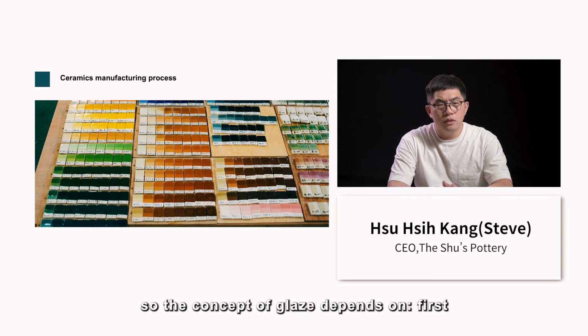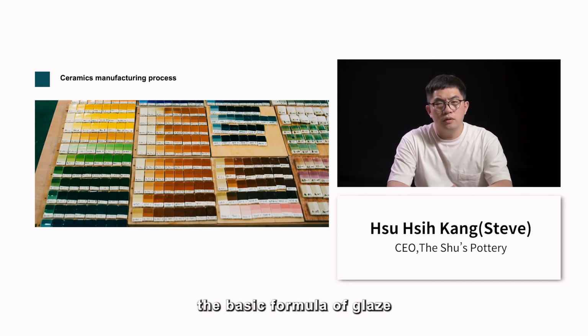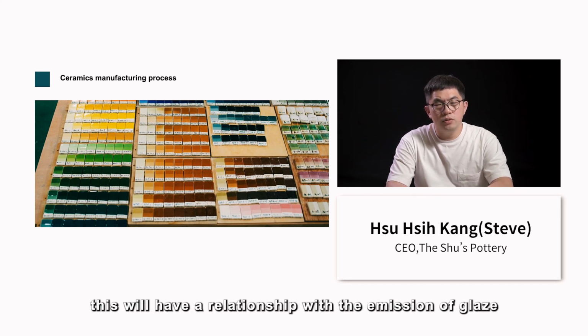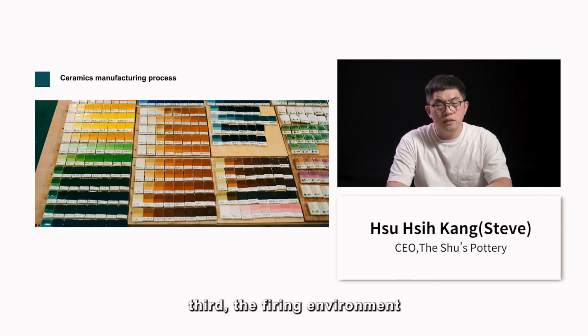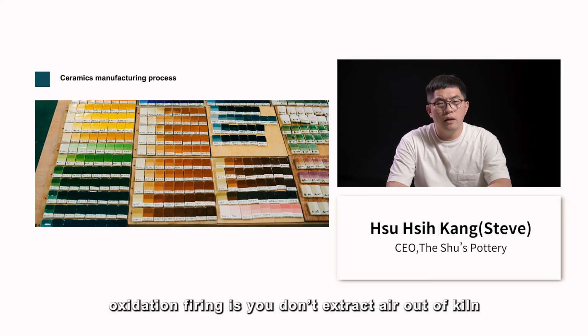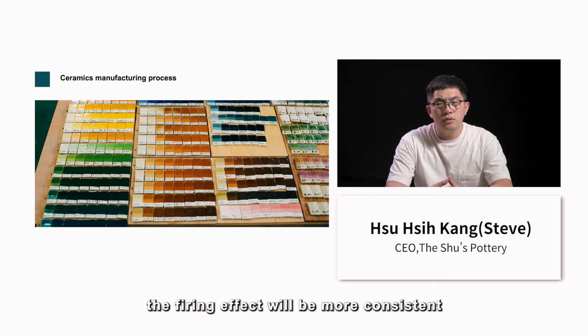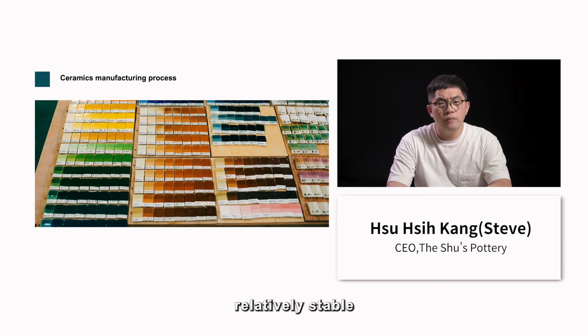So the concept of glaze depends on, first, the basic formula of glaze, whether it is transparent or milky, and second, the material, whether it is clay or semi-porcelain clay. This will have a relationship with the emission of glaze. Third, the firing environment, whether it is oxidation or reduction. If it is an electric kiln, then it is mainly oxidation firing. Oxidation firing is when you don't extract air out of the kiln. The kiln is still filled with oxygen. The firing effect will be more consistent. There will be no reduction or kiln effect, relatively stable. For products with more colors, such as this colored glaze, oxidation firing will enhance yield rate.